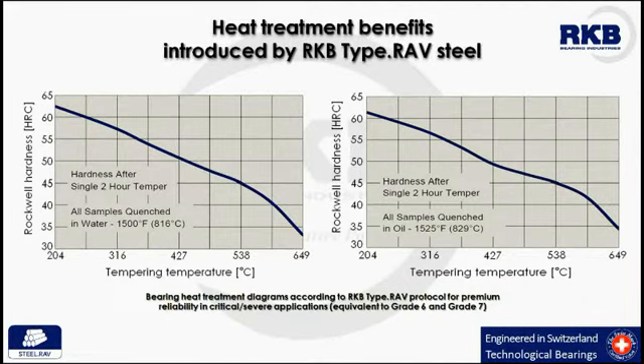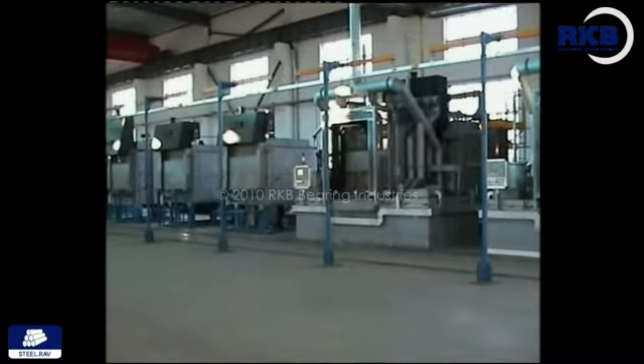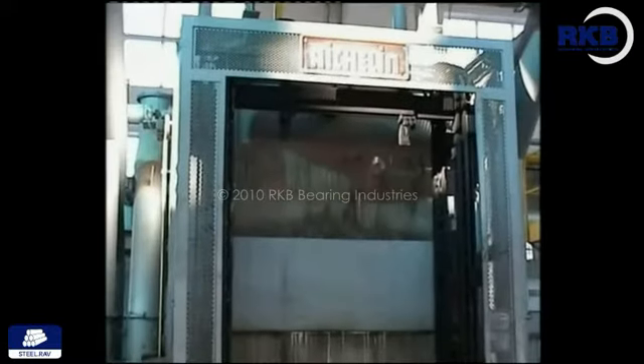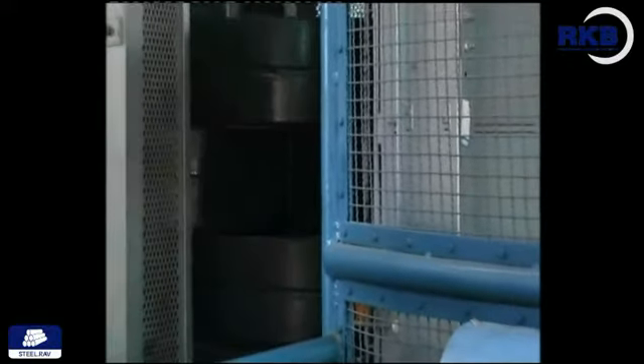Having a proper chemical composition and fine grain structure, the RKB Type.RAV steel capitalizes on special heat treatments to reach a proper hardness, 58 to 63 HRC, useful for wear resistance and dimensional stability. In this movie clip, you can see a phase of the temperability process in our RKB T3 manufacturing plant. By adopting the RKB Type.RAV steel, there are relevant advantages in the temperability property during heat treatment operations, and in particular in performing the isothermal bainite treatment.